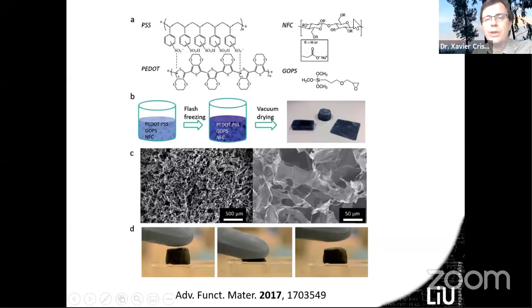We mix that with nanofiber of cellulose, and we cross-link that with a silane agent to make it robust, and also elastomeric to some extent. So you obtain this kind of porous structure. Here you see the SEM image. This is an aerogel, so it's very porous.